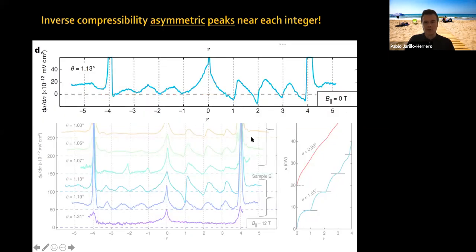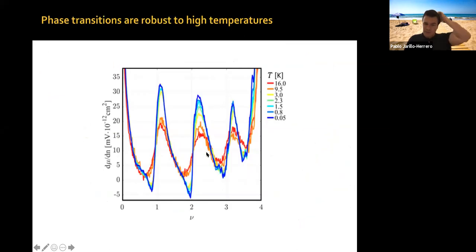Let me, as I told you, in these higher quality devices that we're looking at now, even at zero parallel magnetic field, you have all of these features present, that were shown here earlier in a finite parallel magnetic field. Now you can also do temperature dependence of these inverse compressibility peaks. I'm showing here only for electron doping, okay? And you can see that these peaks persist all the way to 16 Kelvin.